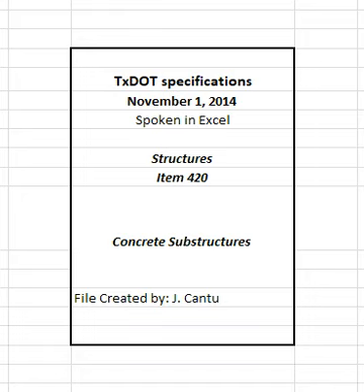4.1.1 Setting Forms. Attain at least 2,500 psi compressive strength before erecting forms on concrete footings supported by piling or drilled shafts, or on individual drilled shafts. Erect forms on spread footings and culvert footings after the footing concrete has aged at least 2 curing days as defined in section 420.4.10, curing concrete. Place concrete only after the forms and reinforcing steel have been inspected by the engineer.